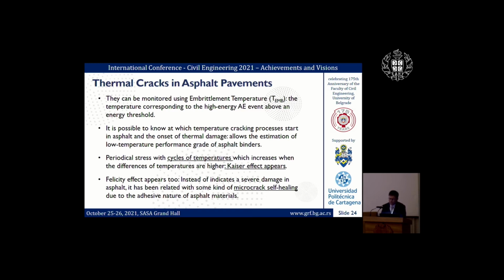So if you are measuring the acoustic emission energy events, and then correlate them with the temperature, when you have the highest one, then you have this temperature that can be an estimation of at which temperature the cracking process is going to start.